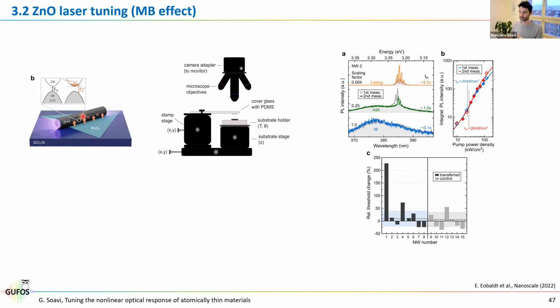However, we found out that we can use the deterministic transfer also for nanowires, and by doing that we can make any type of heterostructure where we can control the alignment and the amount of overlap between the TMD and the nanowire. So the first thing that we had to do was to check that when we do the transfer, we are not affecting the lasing properties or the optical performance of the zinc oxide.